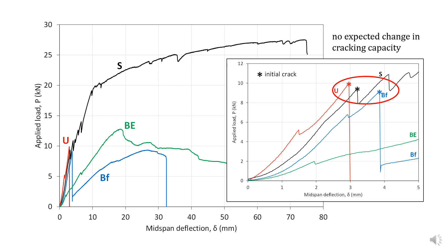In the case of bamboo-reinforced concrete, we see rather precipitous drops in capacity. The capacity does pick up a little bit once the bamboo is engaged. However, the capacity really shows very little reserve over the cracking loads of these beams.